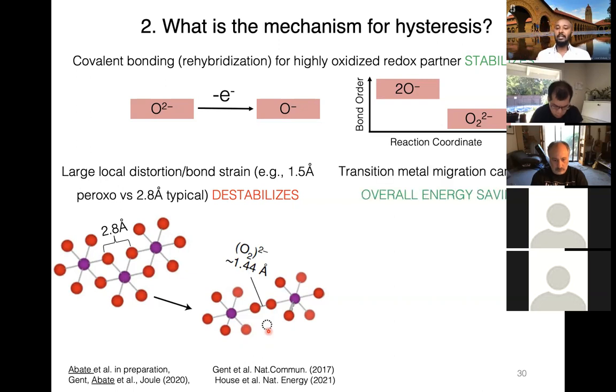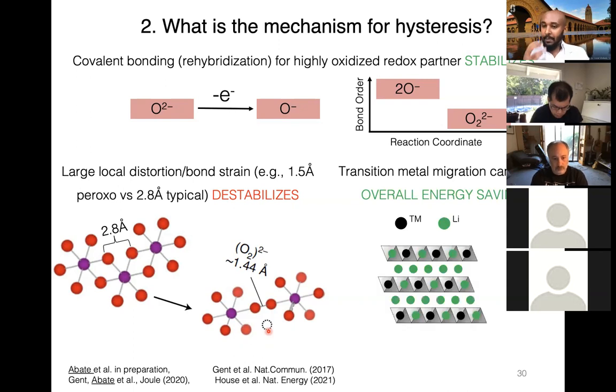So what I mean by this process is that if we have such a layered system that I mentioned in the beginning of my talk, these are layered systems where we have lithium in between, and then we have the metal on the transition metal layer. Upon charging, we remove the lithium, leaving behind this vacant site in the system where the transition metal can move to occupy this site, thereby alleviating the bond strain created by this short oxygen-oxygen bond formation.